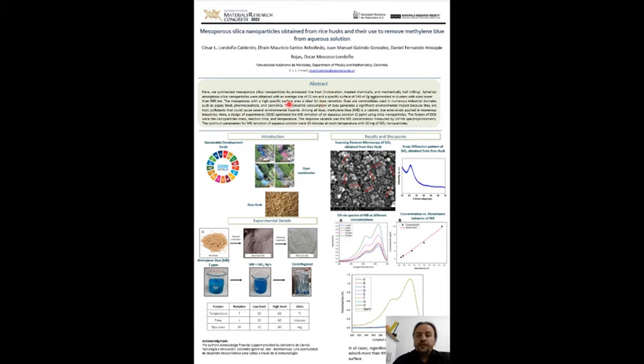Here we obtain silica nanoparticles from the incineration of rice husk, a chemical treatment of the ash, and mechanical ball milling. The size, shape, specific surface, and cluster size of the nanoparticles were determined. The mesoporous structure and high specific surface area are taken advantage of for methylene blue removal from aqueous solution at 2 ppm of concentration. A design of experiments was optimized to evaluate the effect of factors such as nanoparticle mass, reaction time,